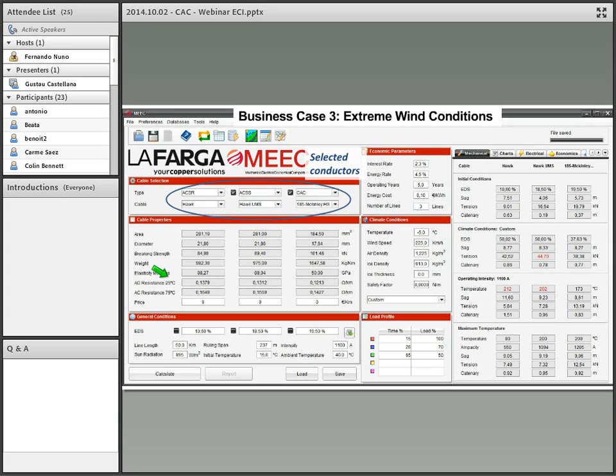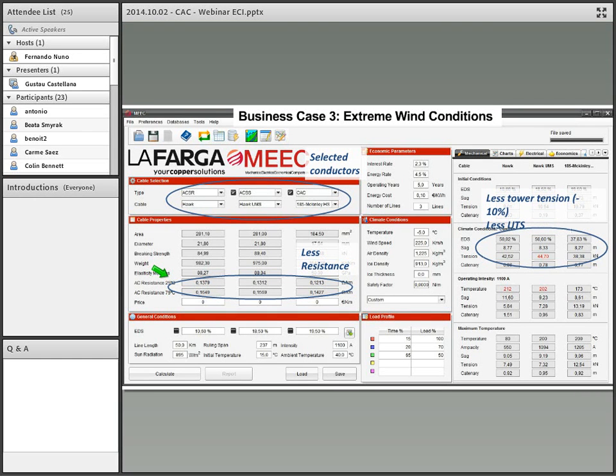So as before, we have less resistance. In that case, due to this wind speed, the section or the diameter is getting really important. And you can see here that even if we start with a higher initial tension, so you can see here how the CAC has higher initial tension, our solution, the copper microalloy solution, has 10% less tower tension, less UTS, and has more than double ampacity with the same sag. So this would be able to cope with an N-1 solution. So this is a really interesting solution for these wind speed cases.